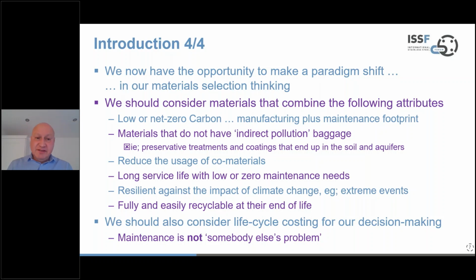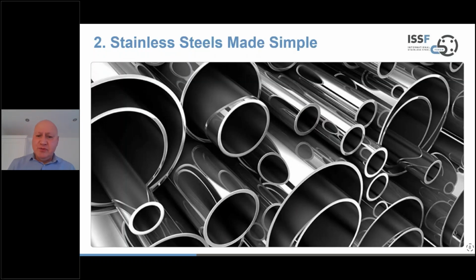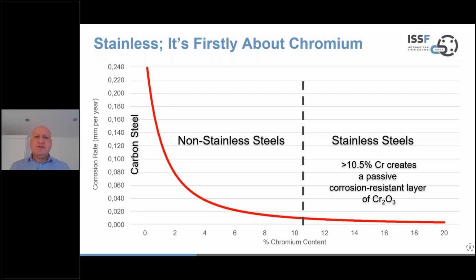So having set the scene, I would now like to move forward and just try and talk about stainless steels in a fairly simplistic and memorable way. So firstly, for most people we understand, for some people maybe not, but it's all about chromium to start with. And this chart here shows, with the y-axis on the left, corrosion rate in millimeters per year, and on the x-axis on the bottom, chromium content in steels. And you have a red line curve that shows how the corrosion rate develops as you add chromium. And basically, the more chromium you add, the lower the corrosion rate of steel products.